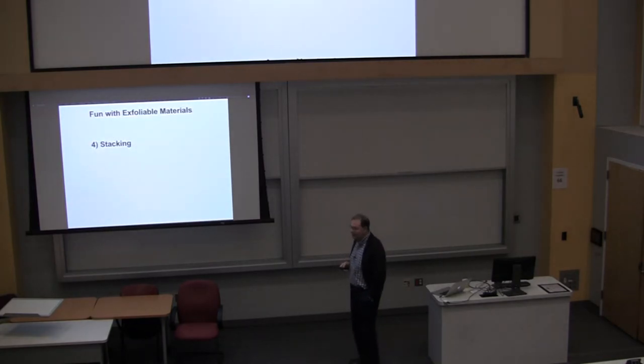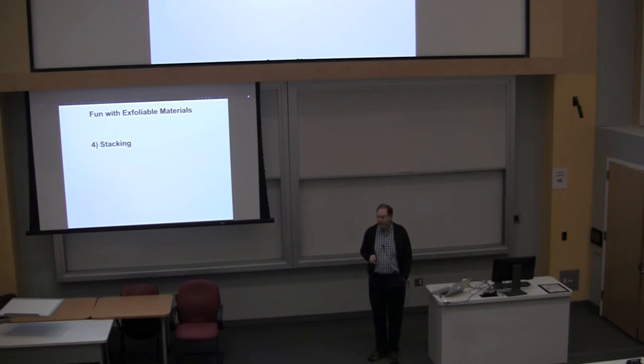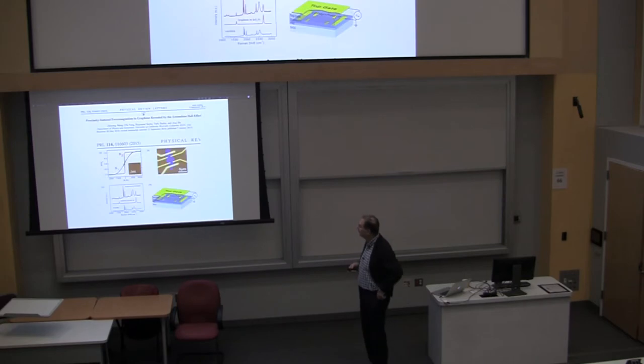All right, so the other thing you could do with exfoliable materials is stack them together in different ways. Right, you can stack them up. Here's an example where they put graphene on top of yttrium iron garnet. Yttrium iron garnet is a ferrimagnet, used a lot in spintronics. They put a piece of graphene on it, and they measured an anomalous Hall effect in the graphene, showing that there was some magnetization from proximity effect in the graphene. That was nice.